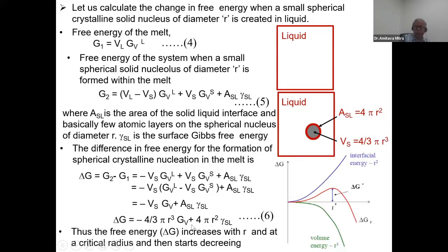Now it has two components. One is the volume component, which is negative, and it has a positive component, that is the interfacial energy. So if we combine these two, it gives a peak and then goes to the negative side. So there is a critical diameter, critical radius, where free energy increases up to the critical radius and then starts decreasing. So we are very much interested to find this critical radius. What is this critical radius?